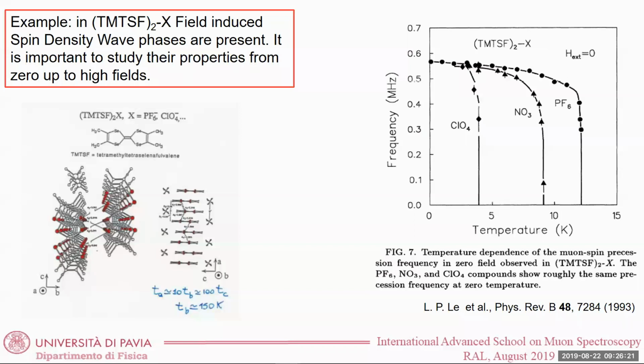Okay? And so how to probe the system in zero field before I perturb it with a magnetic field which can induce this spin density wave phase? Well, with MUSR. And this is what we did in this work, Lee and co-workers. And we studied different families of these organic conductors. And what they measured in this case here is the spin density wave order parameter just by making zero field MUSR. Okay?